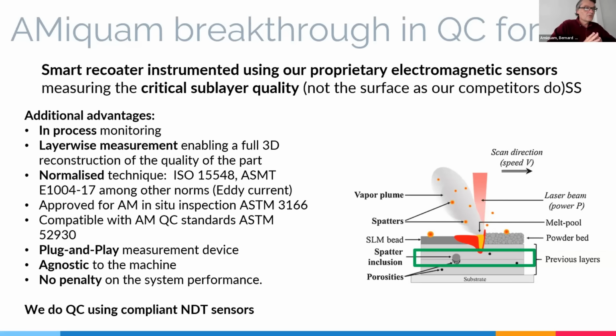So our proposal is to use low frequency electromagnetic waves, also called eddy current, to probe the response of the material at depth, something like between 0.5 and 1 millimeter. So you all know, in laser powder fusion the layer thickness is in the range of 20 micron to 100 micron. So if you can probe the material down to 1 millimeter, you will probe several layers, and within these layers, you can detect defects. Now, the most important point is that we are not inventing a technique. We are bringing an existing technique, called eddy current, which is well established in the metal industry. We are bringing this technique inside the machine. Next.